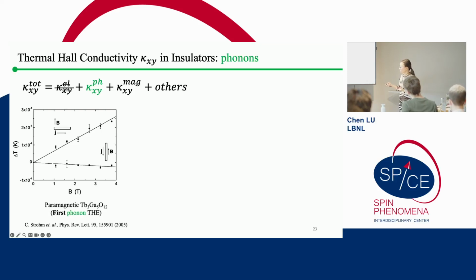So the very first observation of thermal Hall effect coming from phonon was actually done back in 2005 in a paramagnetic insulator material, which is called terbium garnet. But back then, the signal itself was very small, and people only observed it in not many different types of materials. So we started to think, okay, maybe the phonon thermal Hall effect is something very rare.